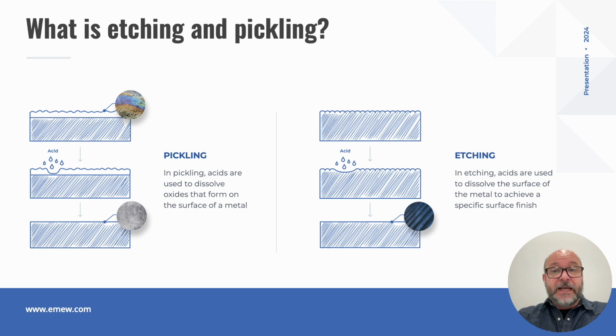Well, simply, etching and pickling are surface treatment processes where a metal product in different forms, flat roll products for instance, sheets or coils, long products such as bar or wire, tubular goods, or forged or cast products are finished in an acid solution. Whenever a metal product is subjected to hot working activities, rolling, extruding, casting, welding, or annealing at the metal's scaling temperature, oxygen will diffuse into the material and form an oxide layer. And acids are used to dissolve this oxide layer to restore the surface of the material to its original composition.